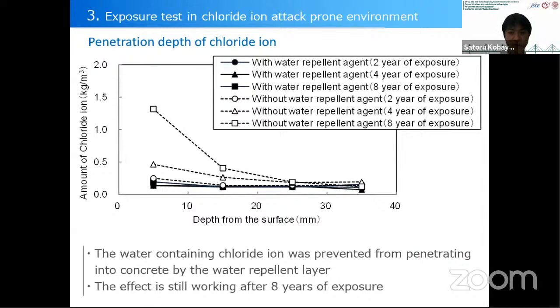This is the result of penetration depth of chloride ion. Horizontal is the depth from the surface, vertical is the amount of chloride ion. The white one is without water repellent agent, and black is with water repellent agent, at 2 years, 4 years, and 8 years of exposure. You can see that it is confirmed that water containing chloride ion was prevented from penetrating into the concrete by the water repellent layer like this. Also, we found that the effect is still working after 8 years of exposure.